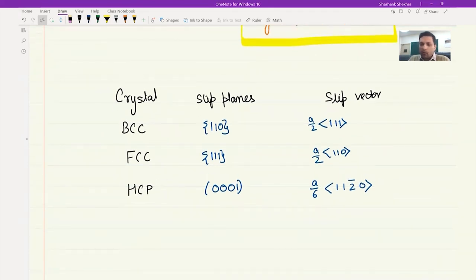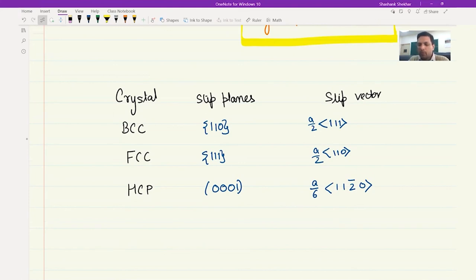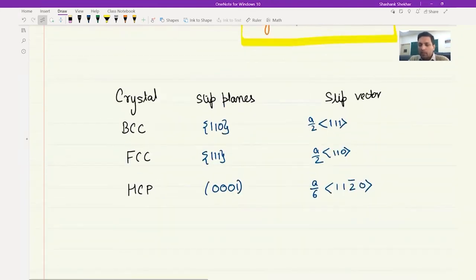So with that, we complete the discussion of slip systems for the various materials. We were able to derive the slip system based on our understanding of resistance to dislocation motion — the Peierls-Nabarro valley present when a dislocation moves. We derived that A should be the densest plane and B should be the densest direction, where A defines the glide plane and B is the Burgers vector. We will look at some examples in the next few lectures. Thank you.